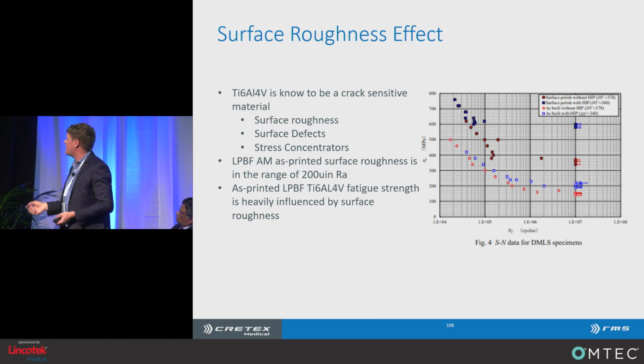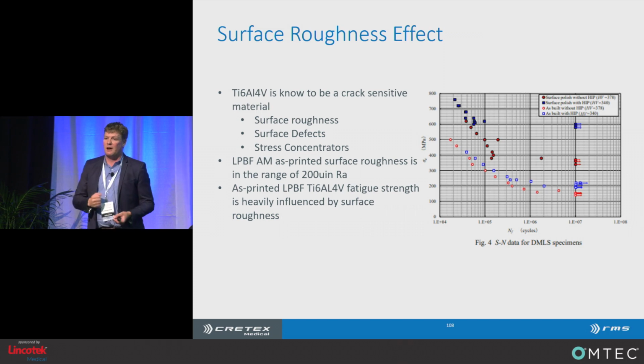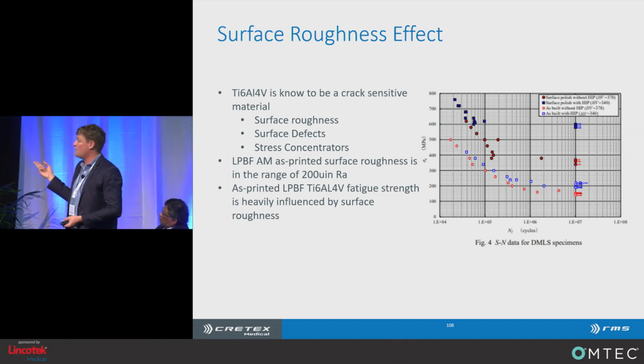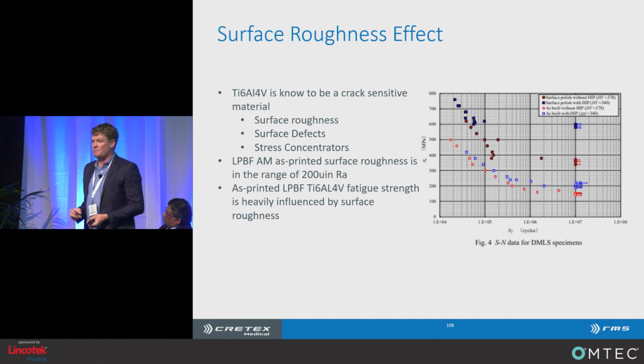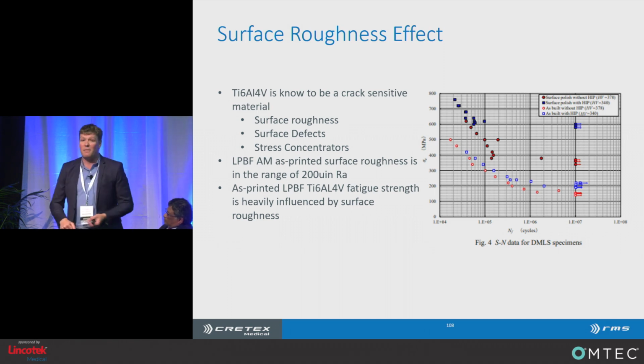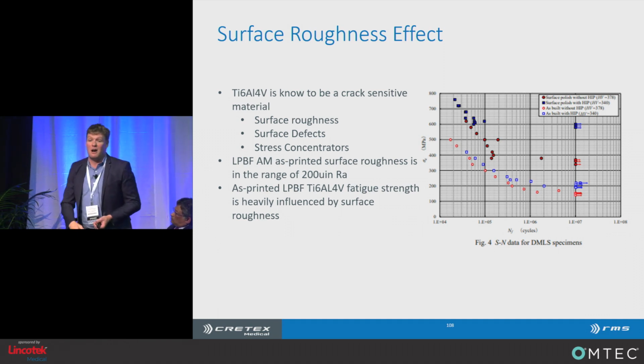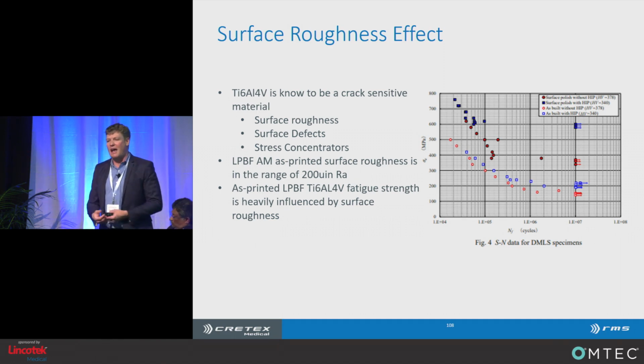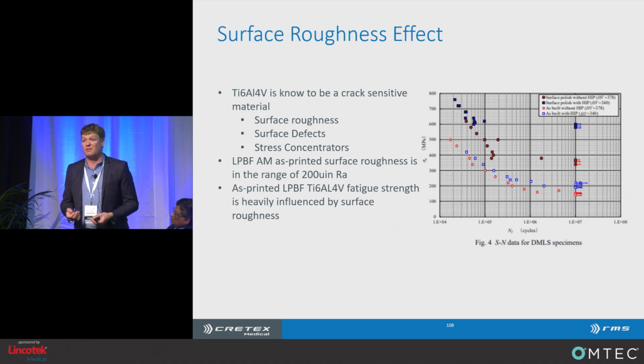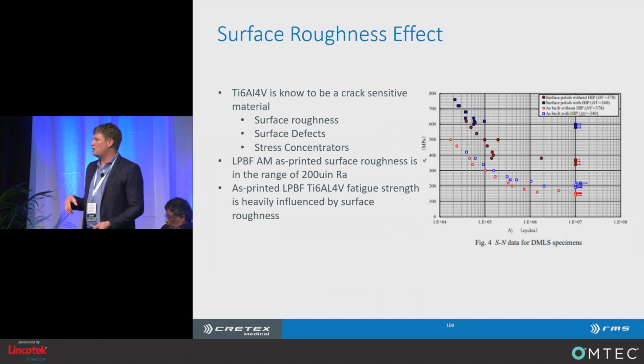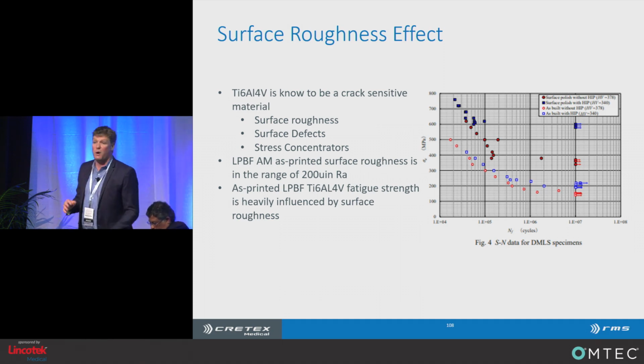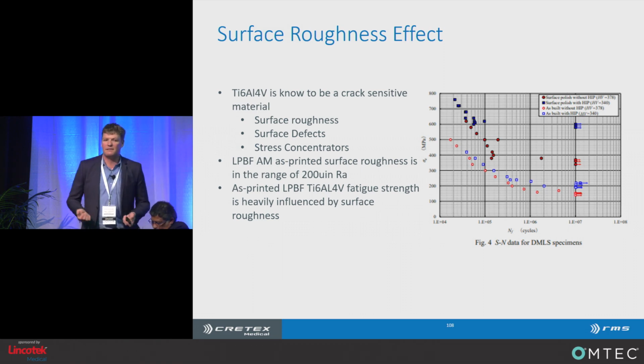This graph here on the right shows a family of, I wish I had a pointer, 4 different groups of fatigue bars. 2 that were highly polished with different static mechanical properties, and then some that are as printed with the surface roughness. And what it shows is that the surface roughness of the fatigue bars totally overwhelms any differences in the actual fatigue strength of the material, right? So that surface roughness and the as printed small micro cracks and stuff on the surface are what dominate the fatigue performance of additively manufactured Ti-6.4.